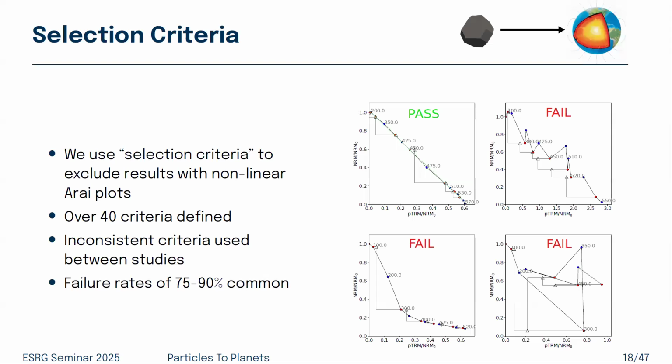So this is a very painstaking process. Each one of these points involves two heatings, which means multiple hour-long cyclings in an oven and then measurement. And you end up rejecting 75% of your data. So this isn't great, right? And this causes problems when it comes to analyzing data.